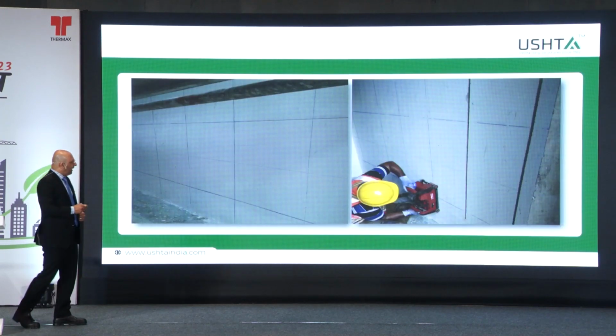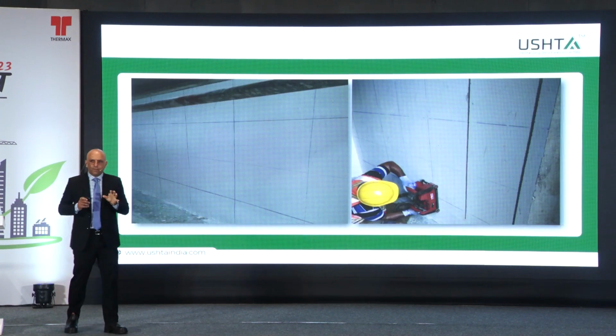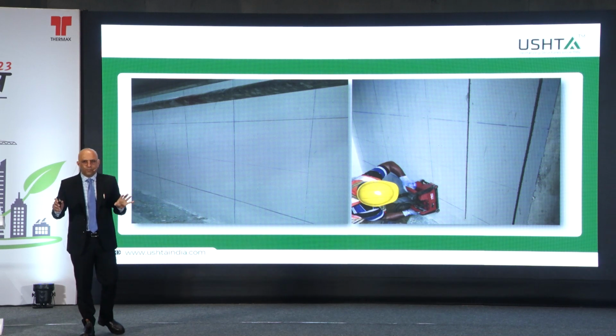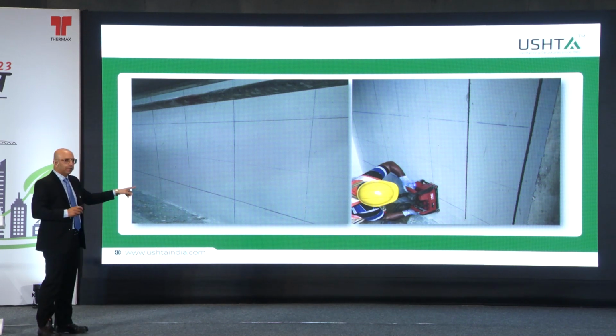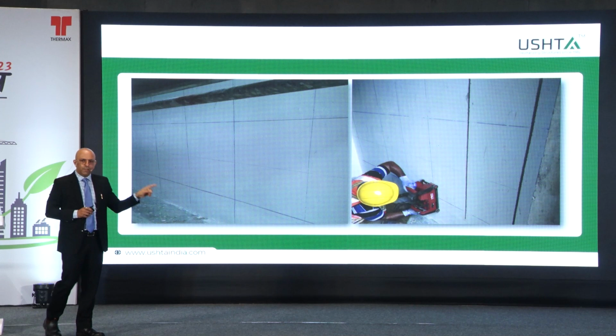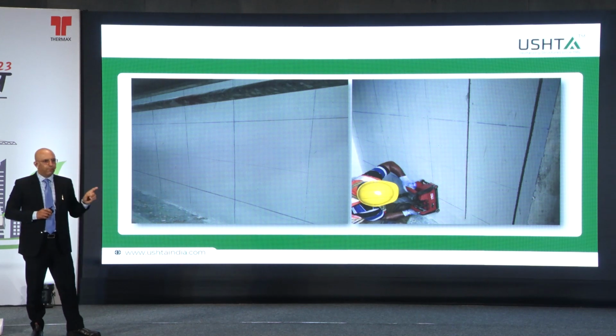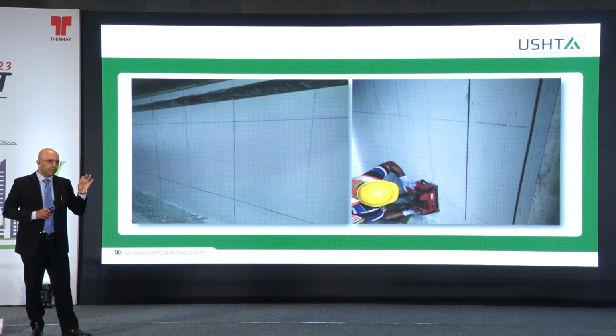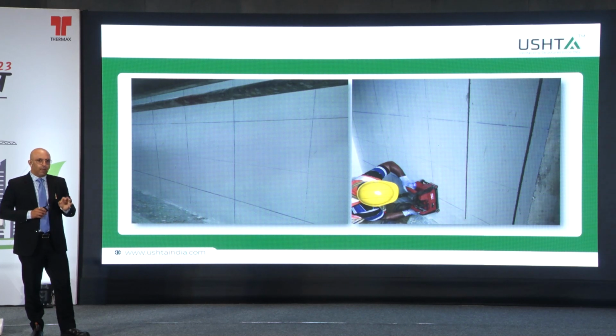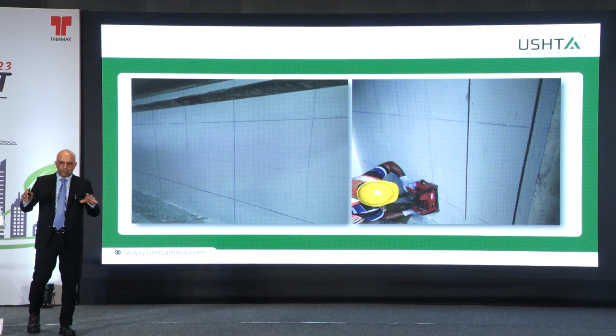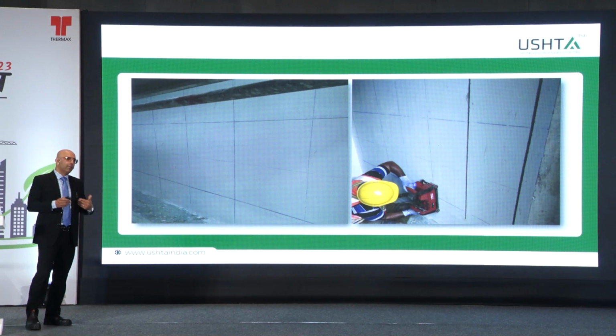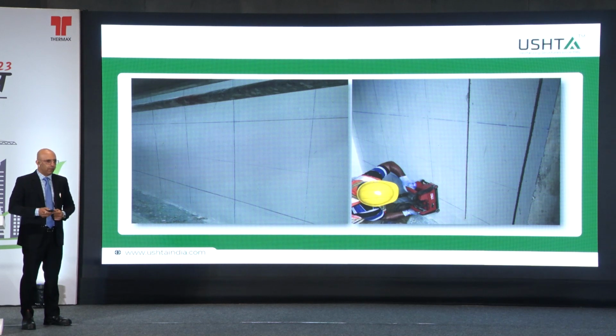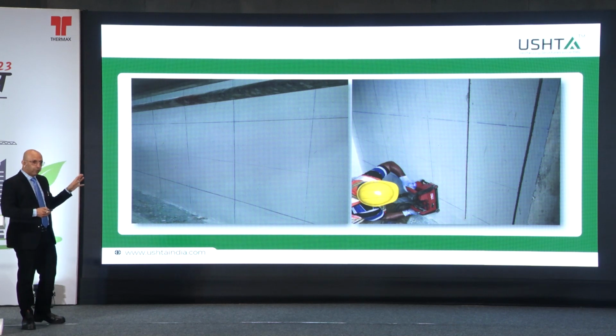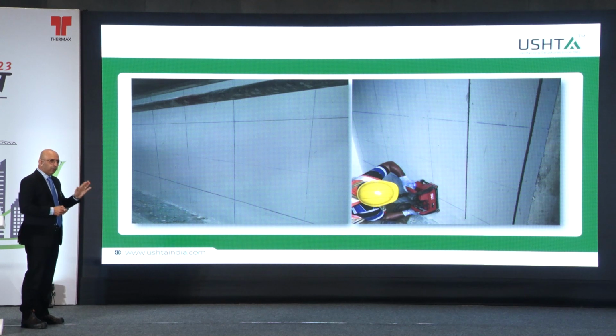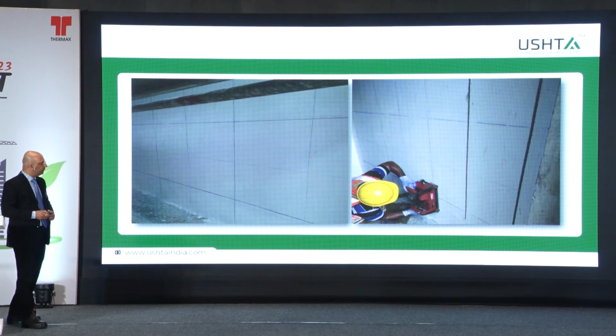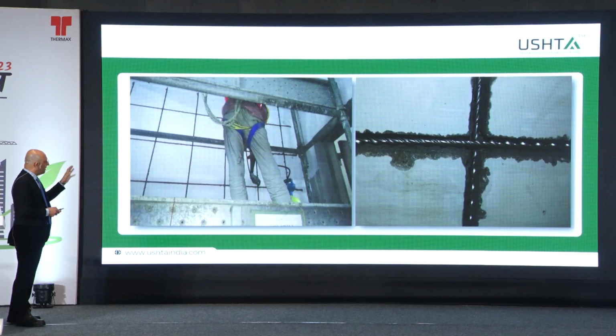In another place, where we could easily transfer this to the walls, we used helical bars because this was very fast. Each wall, when we did it with helical bars, we could give back within almost 13 to 14 hours. And the fiber wrapping, which we did for energy dissipation, took us about 18 to 24 hours. But we completed almost a single wall within that time, including painting, everything finished. So this is a sample wall we did outside.